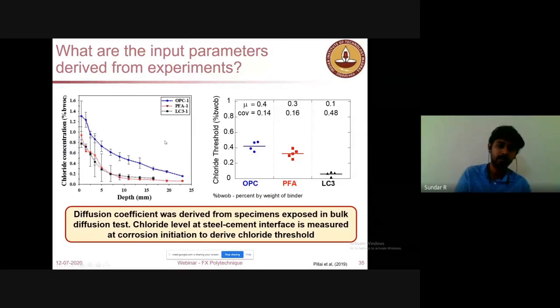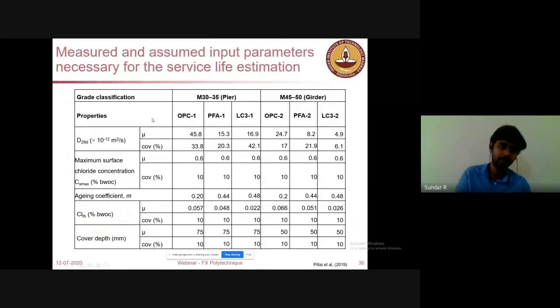So based on that, these are the input parameters that we used for calculating the service life. You need the diffusion coefficient at 28 days, and the surface chloride concentration, that is how much chloride is present near the concrete. That may come from the water around the concrete columns or piers in the sea, or it may be airborne chloride present 800 meters or 1 kilometer away from the coast. That is the surface chloride concentration at the level of the cover of the concrete.